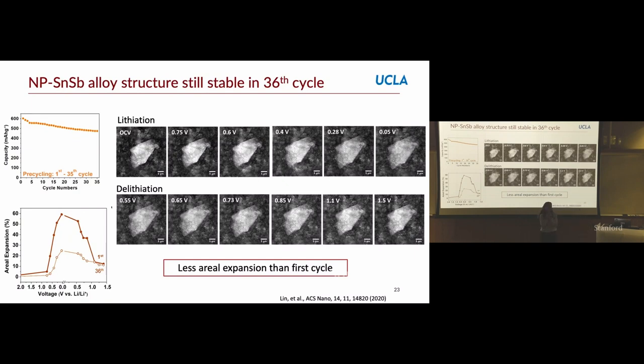I told you that these cells can last tens to hundreds of cycles, which is really important if you want to study not just the very first cycle, but you want to cycle for a while and see what happens, for example, on the 36th cycle. So we took this battery, cycled it at UCLA for 35 cycles. A grad student drove it up from UCLA, and we looked with the X-ray microscope at what the 36th cycle looked like. We were happy to see that we have nice distinct particles.